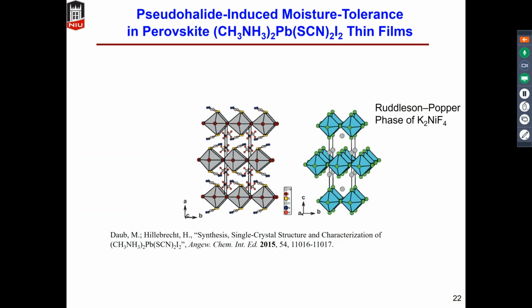There's a German group led by Dr. Hillebrecht. He saw our paper in Angewandte Chemie, and he quickly made single crystals of this pseudo-halide-based perovskite material. And he discovered that this material is actually a two-dimensional material, and it's very similar to the Ruddlesden-Popper type of perovskite material.